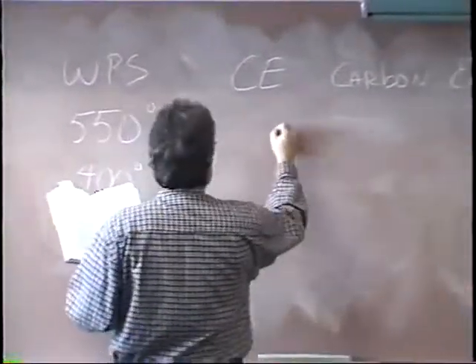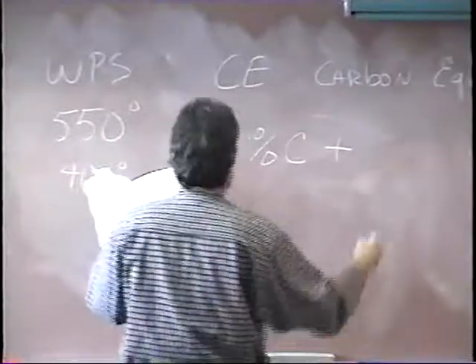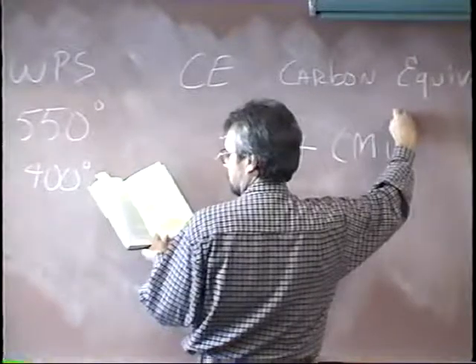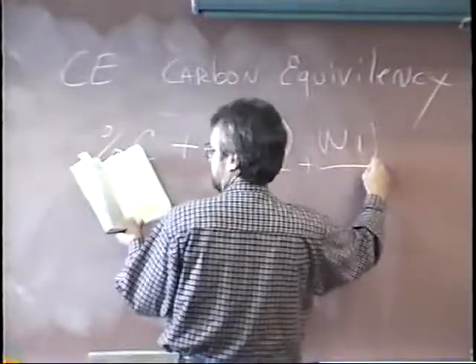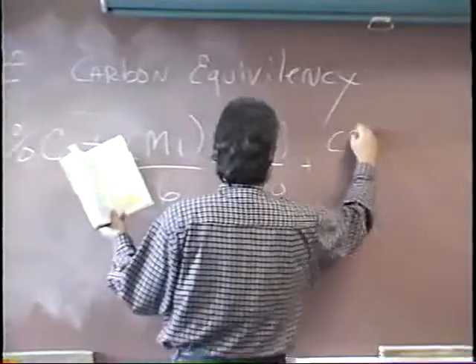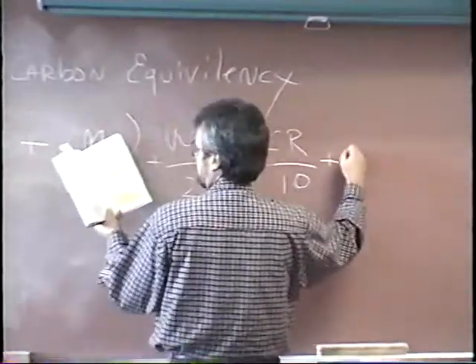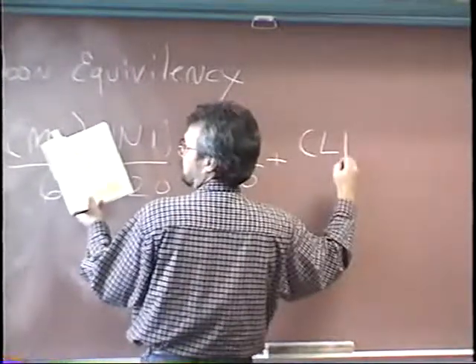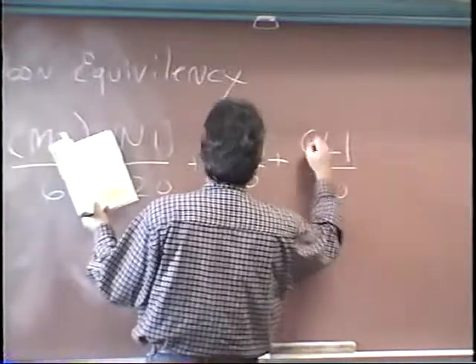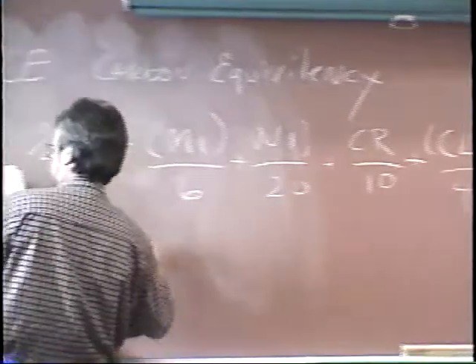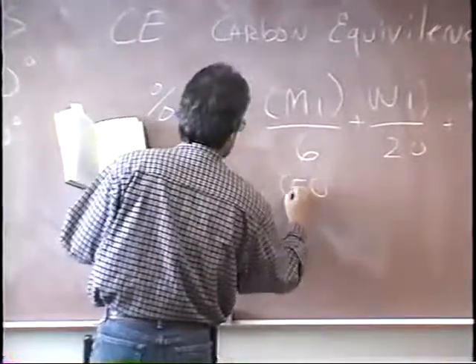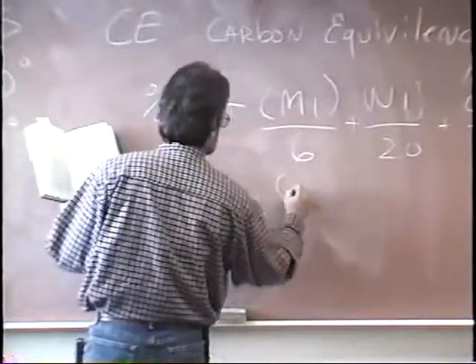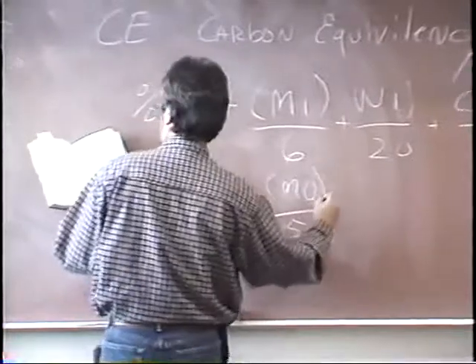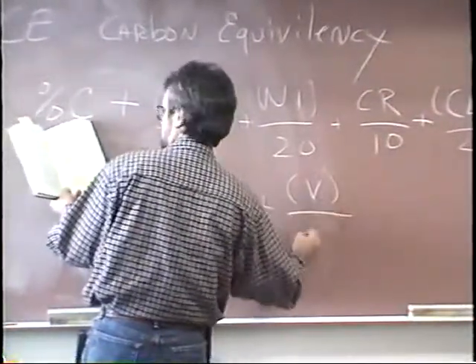And you notice our numbers, I'm going to write this on the board. Our numbers are percent carbon plus however much manganese is in there divided by 6, plus however much nickel is in there divided by 20, plus however much chrome is in there divided by 10, plus however much Cu is in there, I'm afraid I don't know off the top of my head what that is, divided by 40, plus your molybdenum, or moly, Mo, divided by 50, plus vanadium, divided by 10.